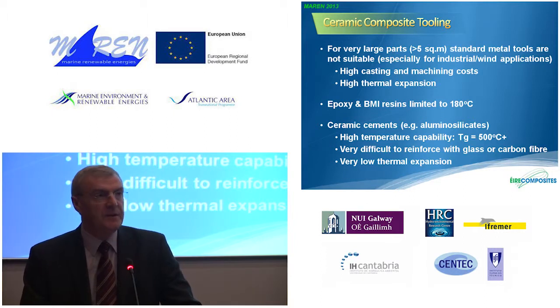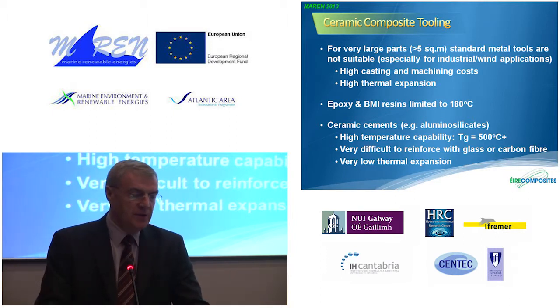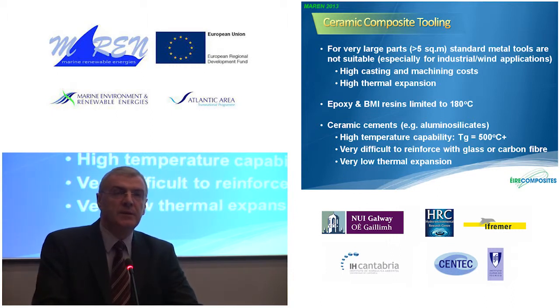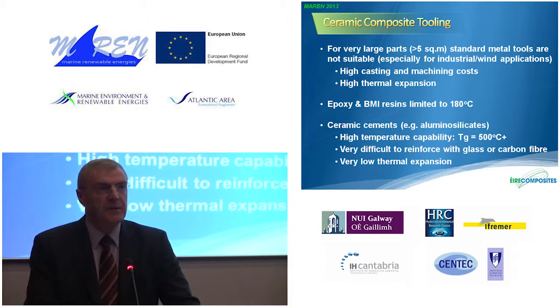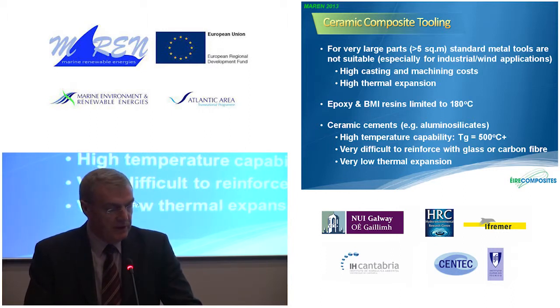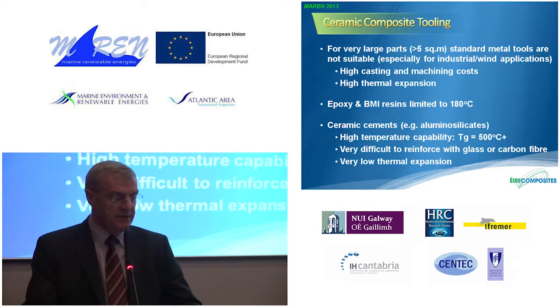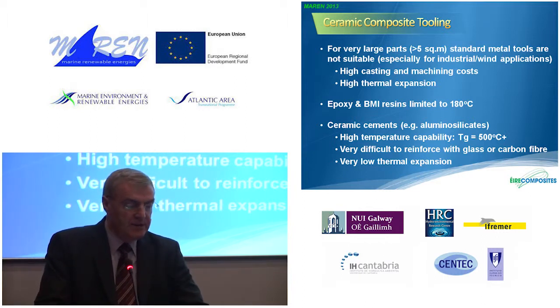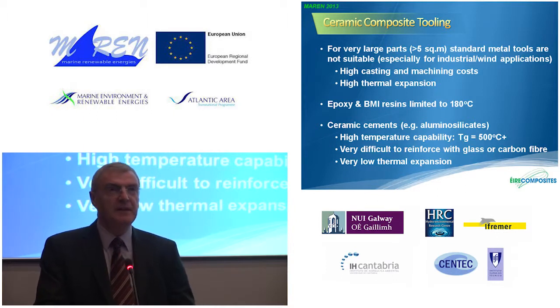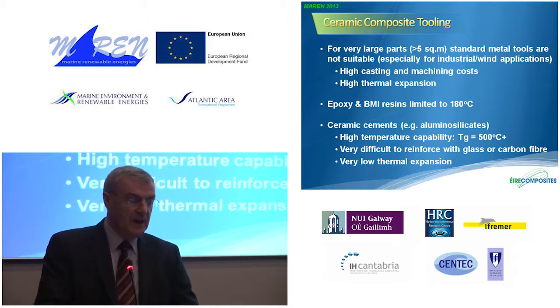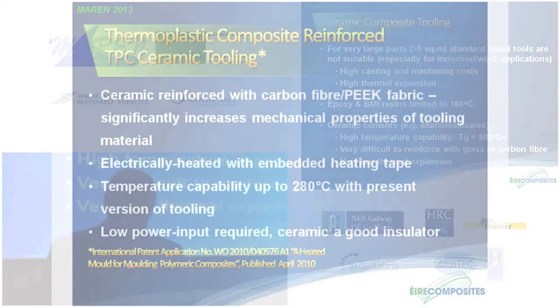Some materials will survive for a short period of time at higher temperatures, but they quickly begin to degrade, and the number of parts that you will remove from a mould after heating to that temperature usually is very low, and the life cycle of the mould is quite short. So we concentrated on materials based on ceramics, and these are ceramic cements. Our alumina silicates have very high temperature capabilities. They, however, are fairly difficult to reinforce with any fibre, glass or carbon, but they have got a very low thermal expansion, which was ideal for what we wanted.